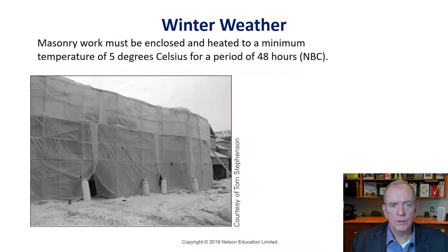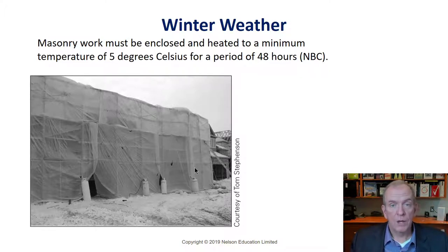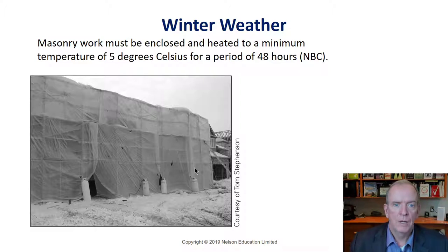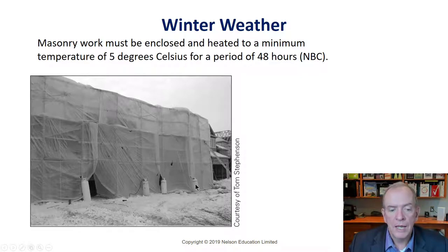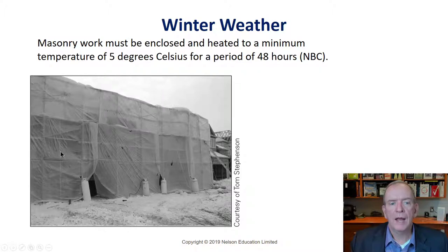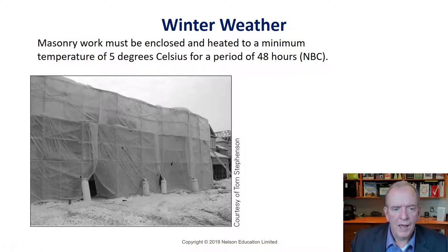Because mortar has water in it, and water freezes, working in cold weather causes problems — it will freeze the mortar. If the mortar freezes when setting up, it'll lose a lot of its strength. The building code requires that new brickwork be kept at a temperature of 5 degrees Celsius for a period of 48 hours after it's set. In cold weather, that typically means the work has to be fully enclosed with heat placed inside using salamander heaters. This image shows such an enclosure taken in approximately minus 15 degrees Celsius weather, done properly by Mattamy Homes.